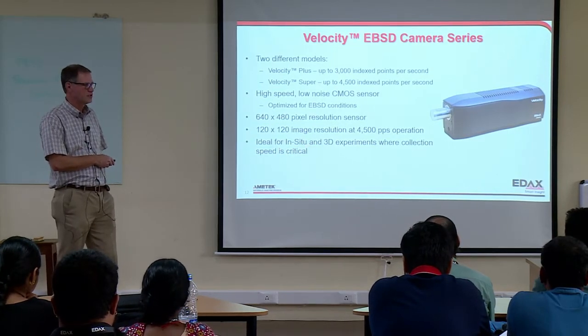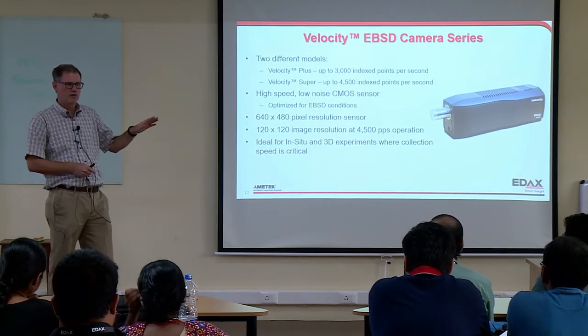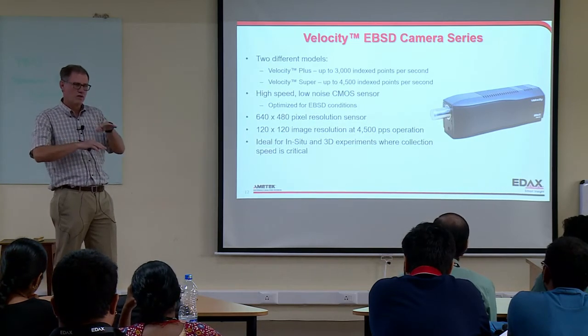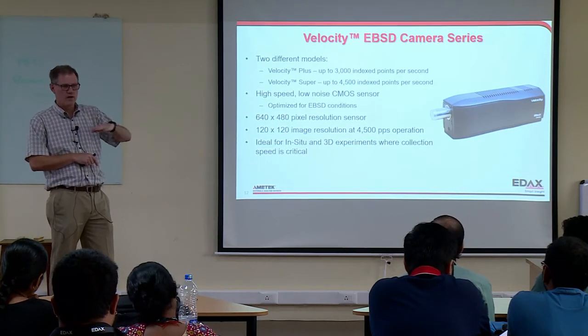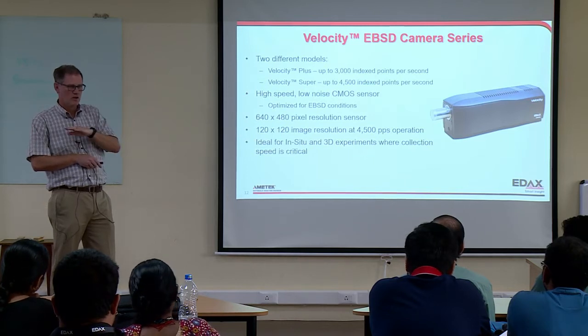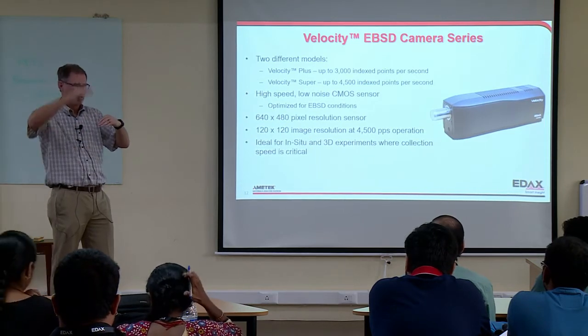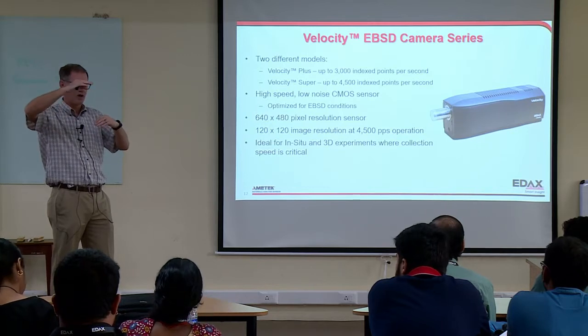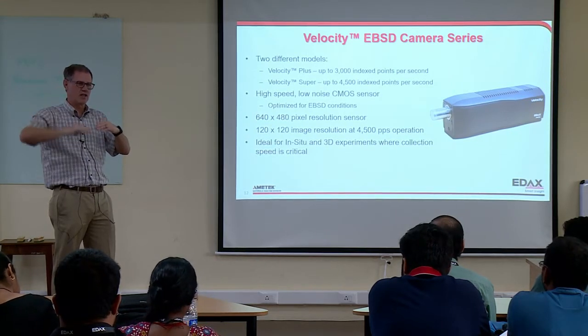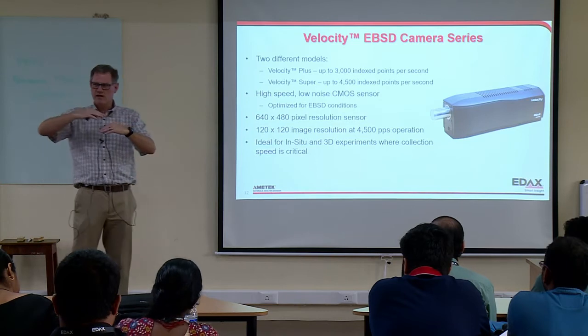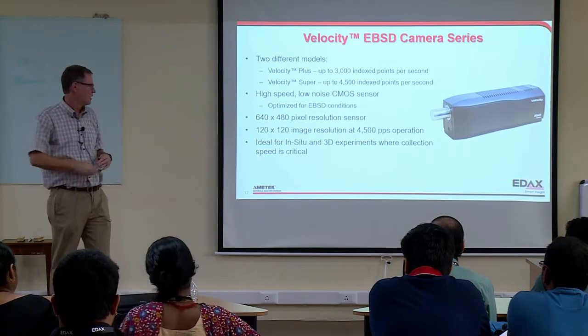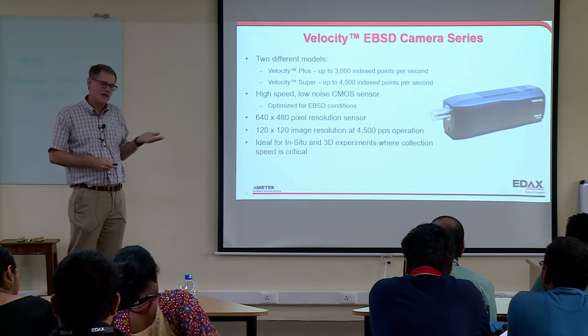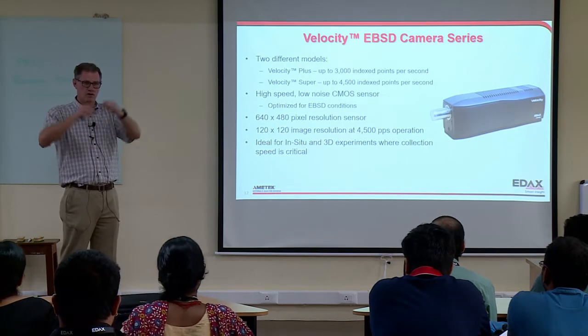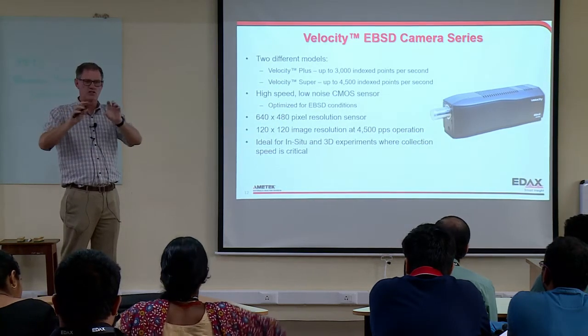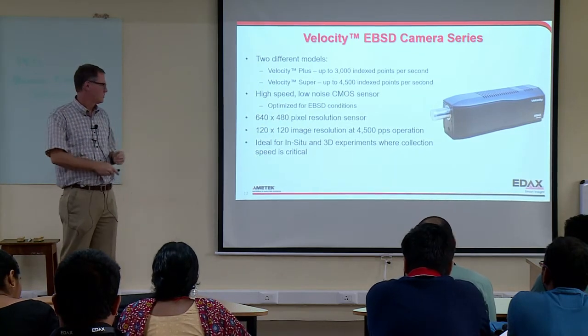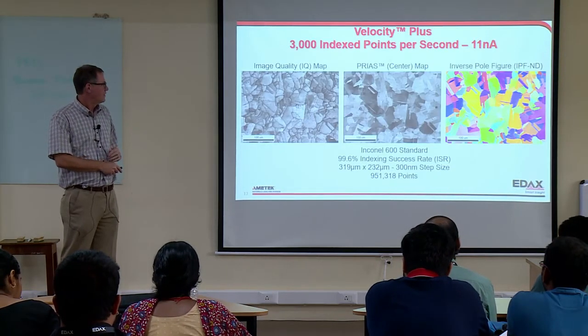A good example is in situ work. Maybe you're trying to recapture recrystallization like I showed before, and we went as fast as we could on that, but we're missing intermediate steps. In fact, while it's scanning, recrystallization is happening. So we might have a different rate of recrystallization at the top of our scan than at the bottom of our scan, and this high speed will allow us to capture that. If you're doing 3D, where you're doing serial sectioning and many, many sections, it can be useful. If you're doing the mosaic scans I showed before, where we're stitching lots of scans together, it's helpful in that situation.